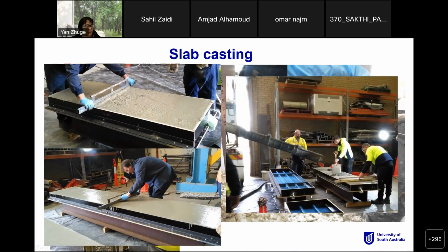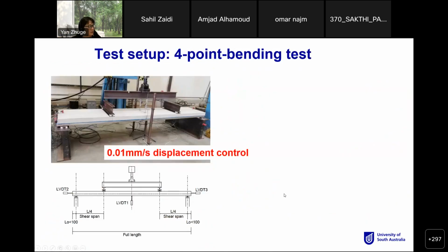So here just shows you some more construction procedures. This is pouring the slab and that's the final finish. You can see the final finish was pretty smooth. Also, in our small test in the lab, we found some rubber was floating at the surface of the slab. But for this real one, there's no floating at all. Everything was very similar to the normal concrete. So there are still some construction procedures. Okay.